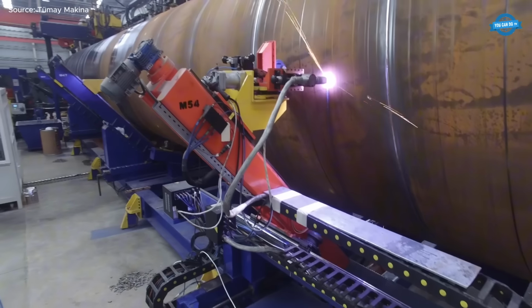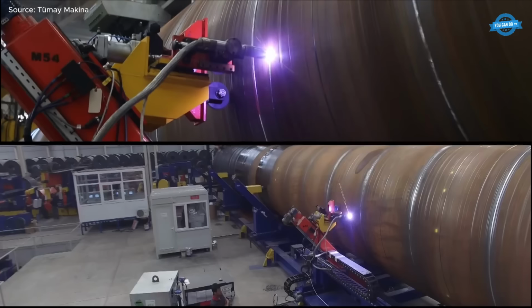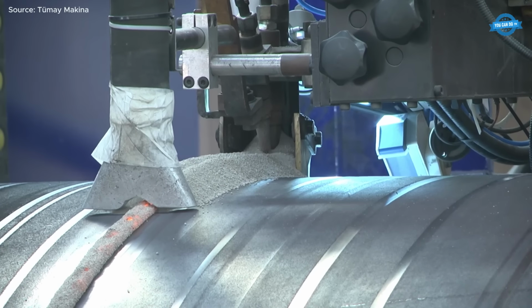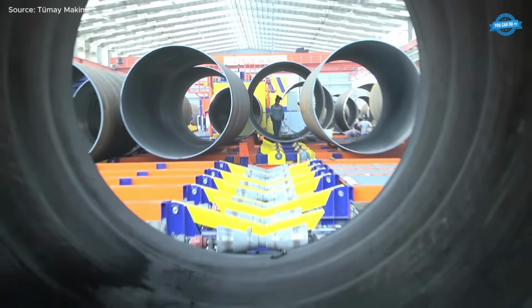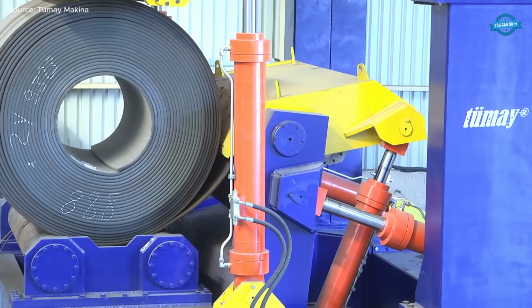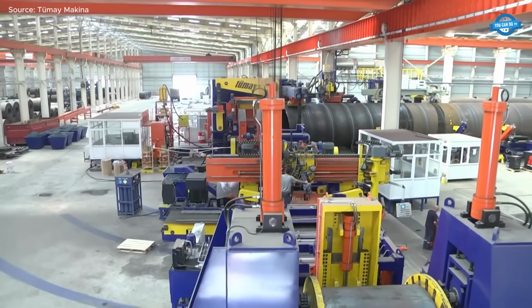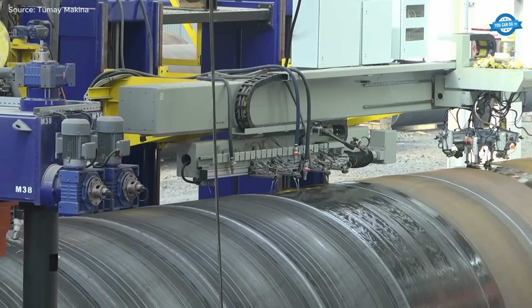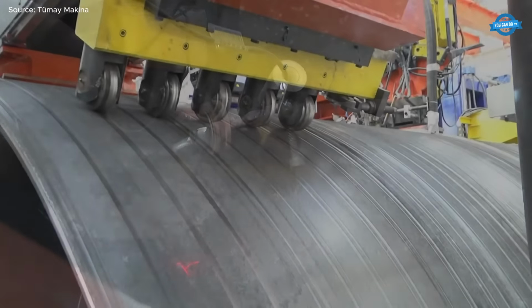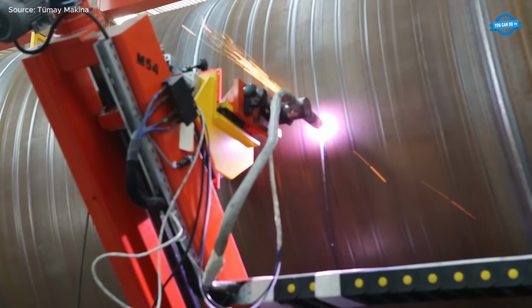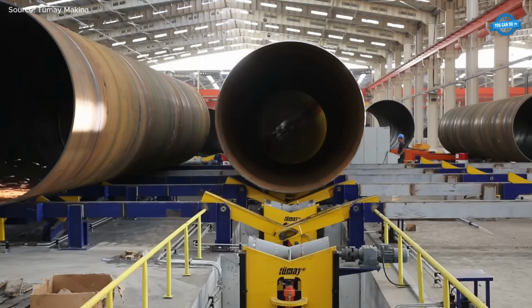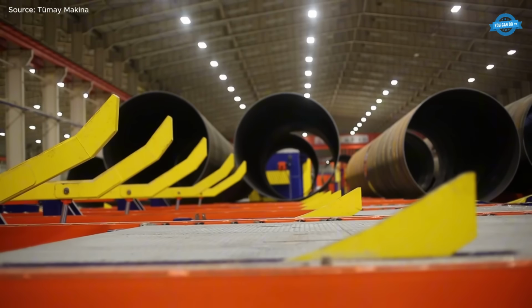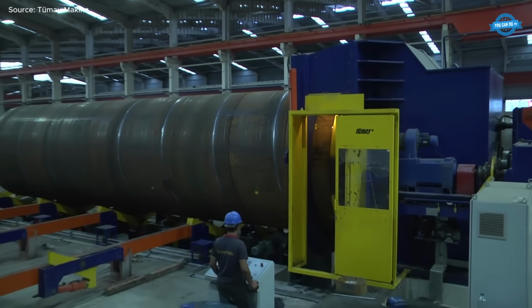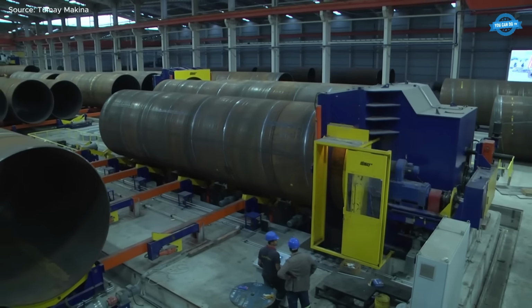Each weld is inspected using automated ultrasonic testing systems that verify the quality of the joint along the entire pipe length. Once the pipe body is formed, automated plasma cutting systems trim the pipe to the specified length. Conveyors and rolling equipment transport the pipes through cleaning and finishing stations before further processing. Additional equipment bevels the pipe ends to facilitate field welding and correct edge distortions caused during cutting.